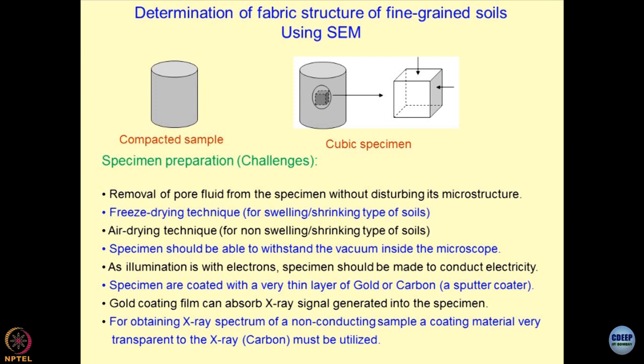Taking out a one-centimeter cube specimen of clays from a triaxial sample and making it a good specimen for studying micro features is not a simple task. When you remove the pore fluids from the specimen, the structure changes because the fluid is packed between the grains. By holding the small cube by hand or applying any force, the microstructure gets changed. Most SEMs work on frozen samples or samples which do not have water, so we use the freeze drying technique.